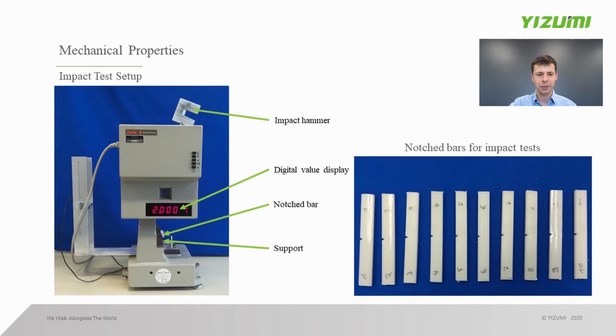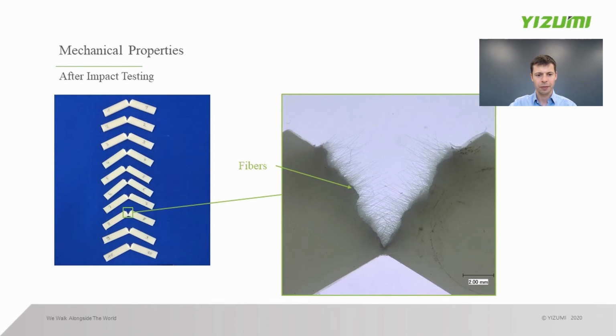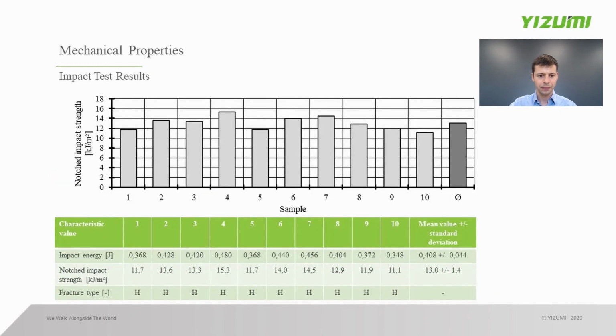The second mechanical test we are trying out is an impact test, where we make these notched Charpy impact test bars, which are then hit by an impact hammer, where the overall impact strength is measured. And the same as before, after the breaking you can still see there's a little notch where the parts are still held together, but you can also see the fibers sticking out of the zone where the bars are broken. And what could also be seen is that we can reach a very high impact strength, averaging at least 13 kilojoules per square meter.